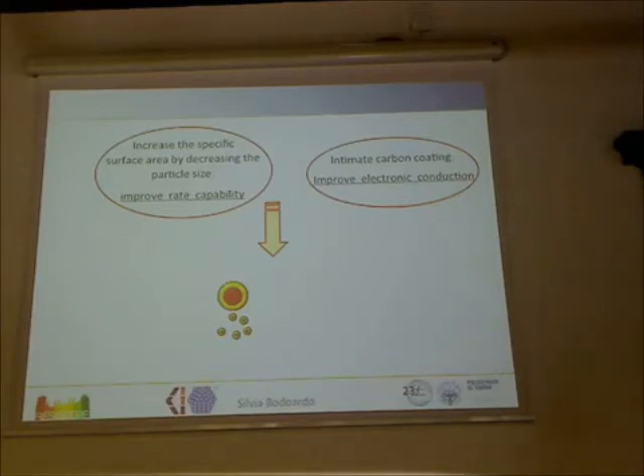So what we can do is also to cover, let's imagine that this small particle is this one now. We can put a carbon layer by playing with the synthesis of the materials, and reducing a carbon precursor, forming a carbon layer directly on the particle, so that now the conductivity is much higher, and moreover we can also put this particle in another amount of carbon-related material, so that we ensure that electrons can pass from the current collector to all the distributed particles.